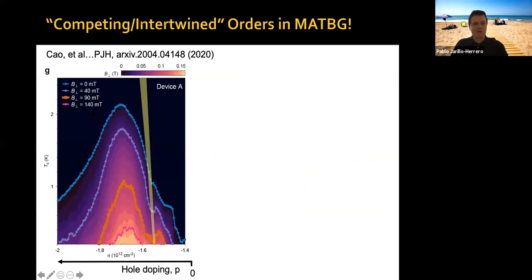You can actually do this continuously. You can look at what TC is as a function of magnetic field. These bands are TC, and these are experimental data as a function of magnetic field. You can see how we have this thing which has a depletion here, and at some point you can split the superconducting dome into two domes. The correlated insulator state is actually here, so this is happening within the superconducting dome. You can see that it exhibits these two domes here. And then if you increase the magnetic field, you kill this dome completely, and you only have one dome left.